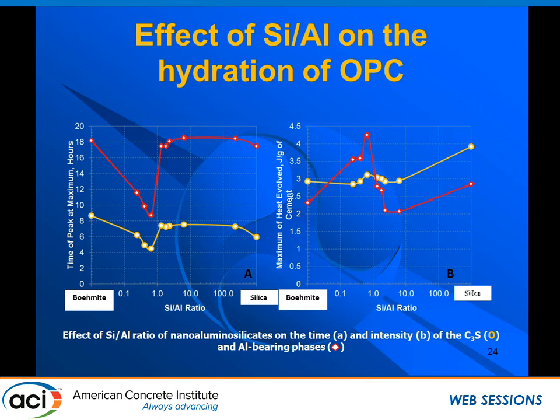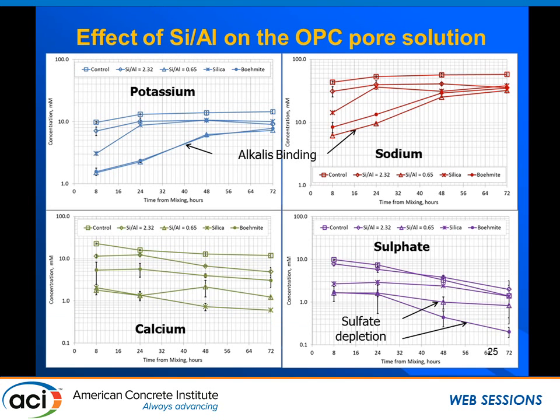If I plot time for the maximum peak of either the silicate peak or the aluminate peak over the silica to alumina ratio, it appears that we have an optimum silica to alumina ratio. If we plot the maximum or the amplitude of the peaks over the same ratio, we also see that there is an optimum silica to alumina ratio.